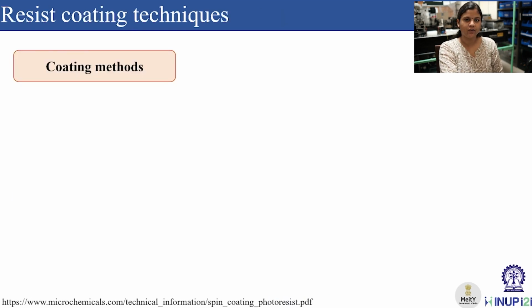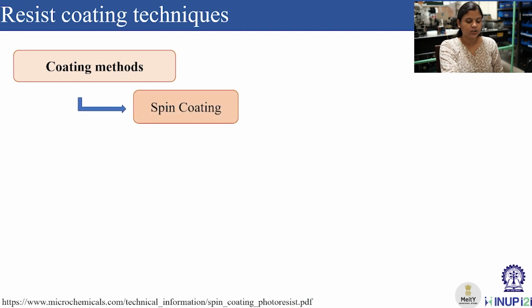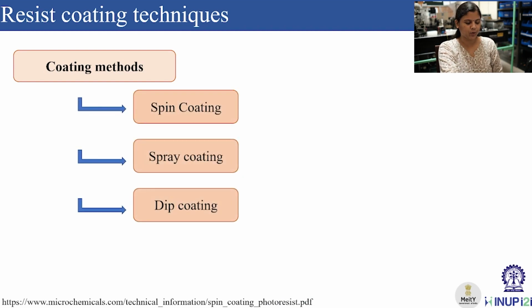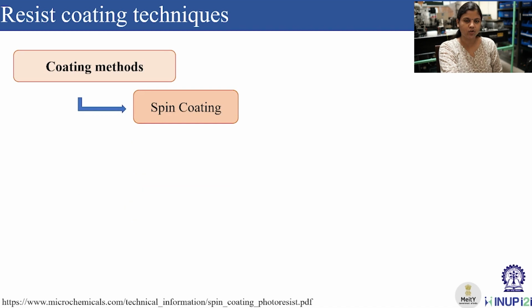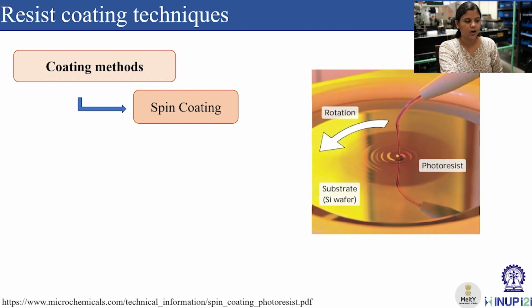So once we have our clean substrate and we have an idea about the photosensitive material, we need to coat it over the substrate. There are various coating techniques available: spin coating, spray coating, and dip coating. Spin coating is one of the most commonly used methods, and we are using spin coating in our lab too. In the spin coating method, a few ml of the photoresist is dispensed on the substrate and it is rotated at high RPM for several seconds. Due to this rotation, a uniform layer of the photoresist is formed over the substrate.